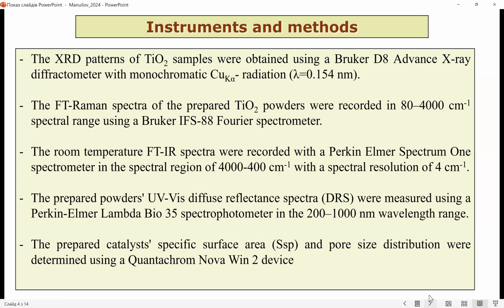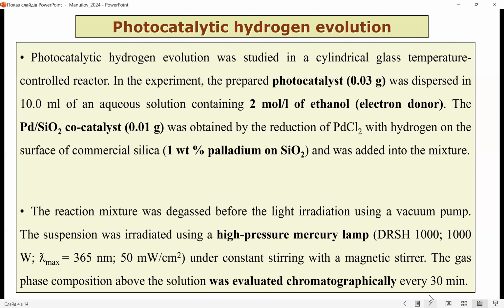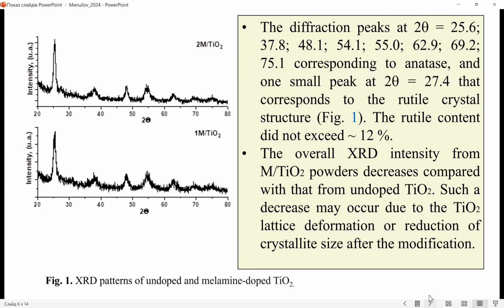These samples were investigated by different methods. You can see these methods on this slide. Photocatalytic hydrogen evolution was studied in a cylindrical glass temperature-controlled reactor. In the experiment, the prepared photocatalyst was dispersed in an aqueous solution containing ethanol as electron donor, and a co-catalyst was added into this mixture. The reaction mixture was degassed before the light irradiation using a vacuum pump. The suspension was irradiated using a high-pressure mercury lamp under constant stirring with a magnetic stirrer. The gas phase composition above the solution was evaluated chromatographically every 30 minutes.